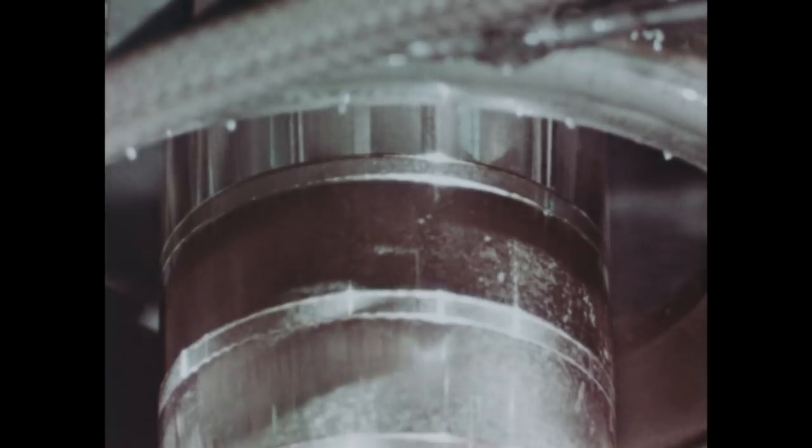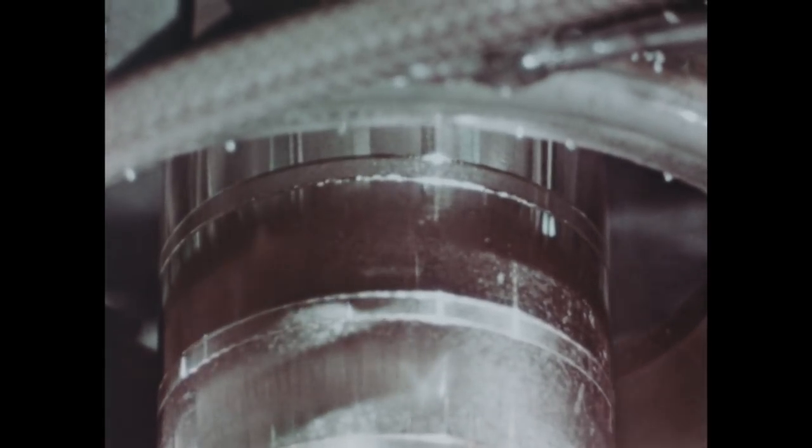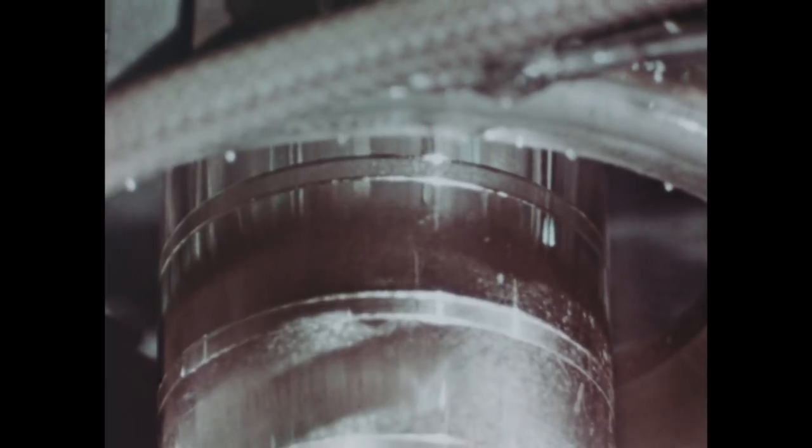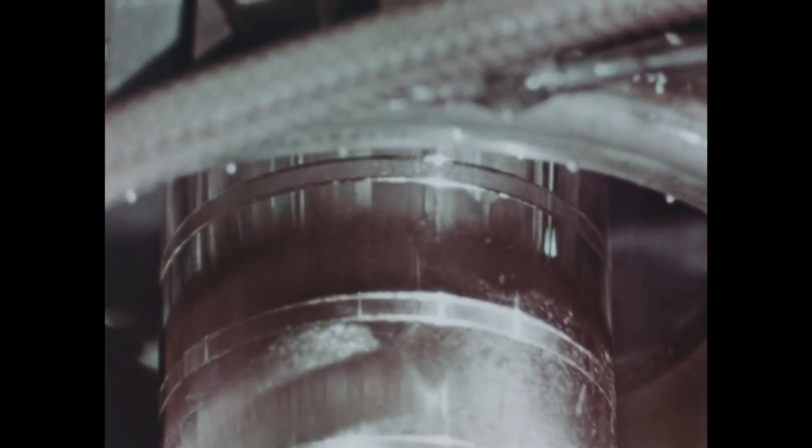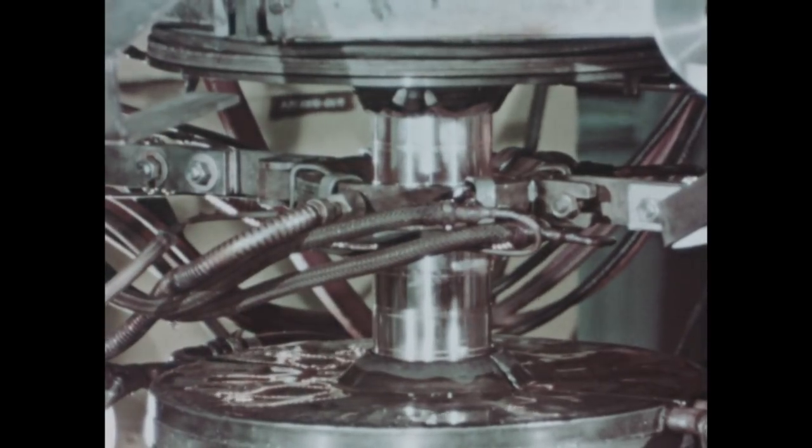It is not desirable to have alloy inside the pipe since it has a lower RF conductivity than the copper and produces undesirable energy losses. Another advantage of this method of brazing is the extremely short period of time that each joint is at the melting point, enhancing dimensional stability. It takes about 40 minutes to braze the 200 pounds of copper.